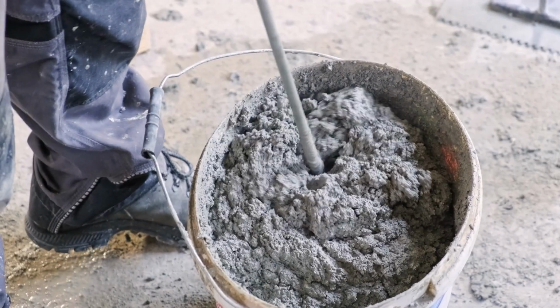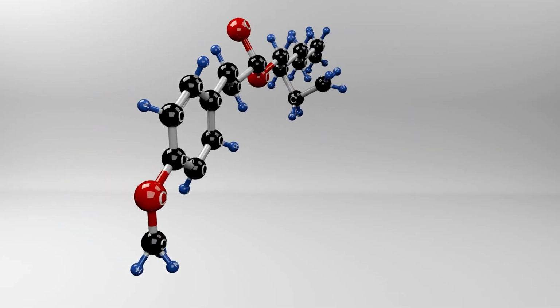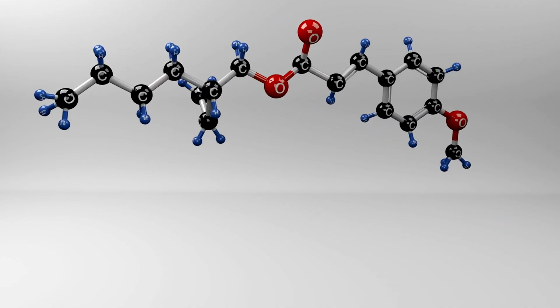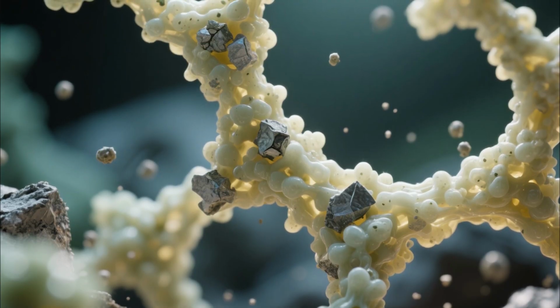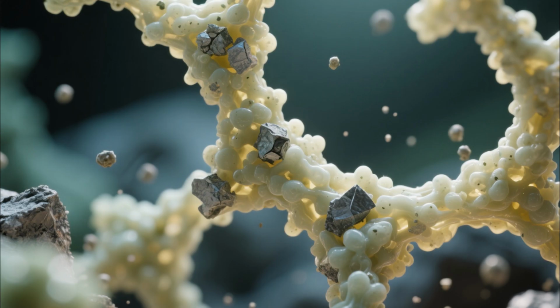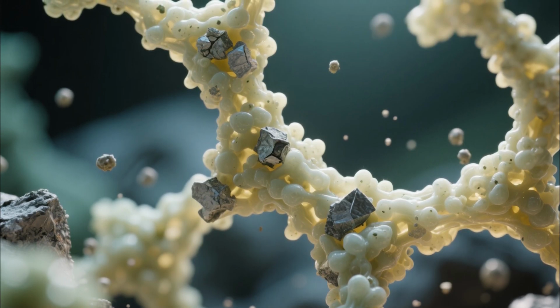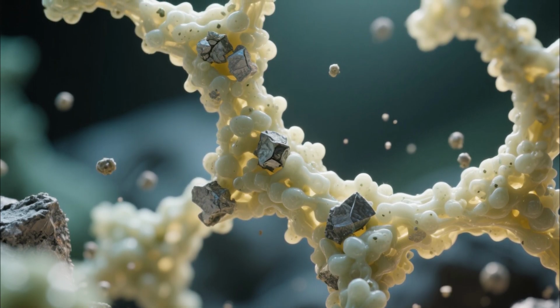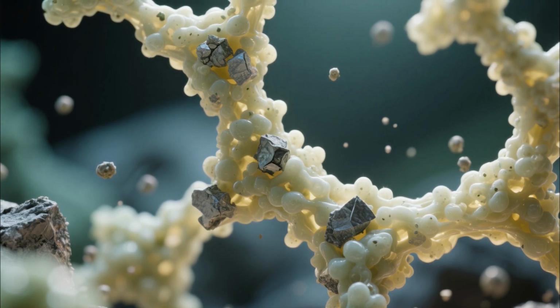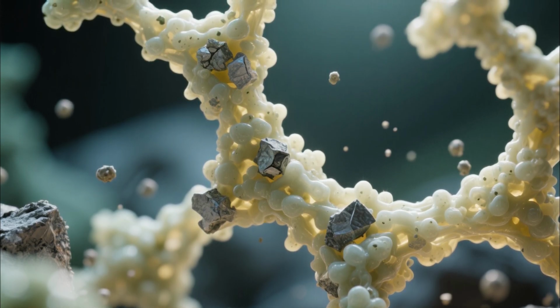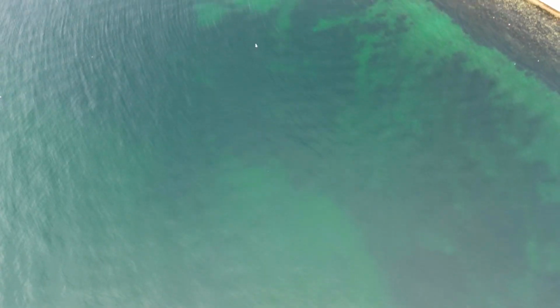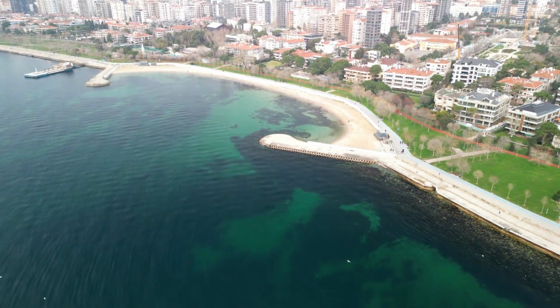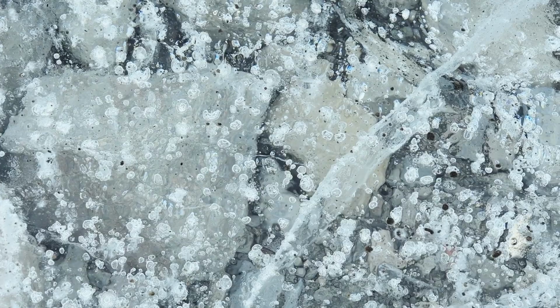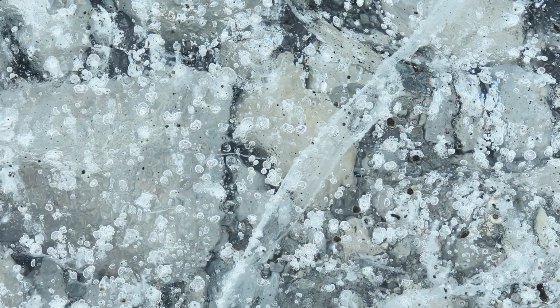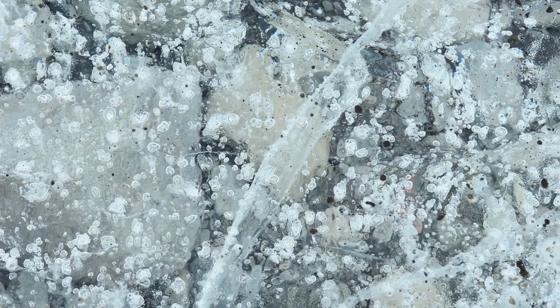Add the pozzolana. Volcanic ash isn't filler, it's a chemical partner. Mixed with lime, it builds calcium aluminum silicate hydrate, C-A-S-H, a binding gel that is more complex than the C-S-H of most modern Portland cements, and can incorporate aluminum from the ash into its structure. That extra aluminum changes how the gel resists ion attack and slows dissolution in hostile environments. In marine placements, seawater isn't an enemy, it's part of the cure.